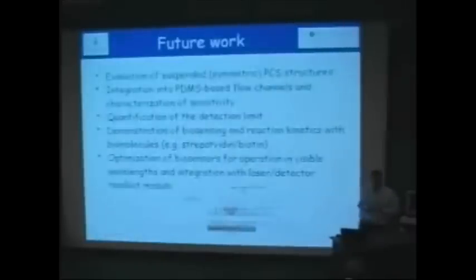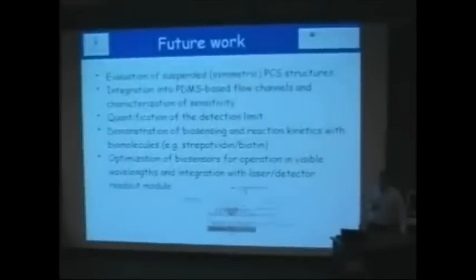And from the fit here, we could see that we get a very good match between the theory and the experiment in our devices. So these are microfluidics devices we make, and the theory and the experiment agree quite well. What are we going to do with it? And I would like to wrap up so we have some time for questions. We're going to evaluate the suspended symmetric devices to allow water above and below the structure. That will give us about 2 to 3 times more sensitivity.